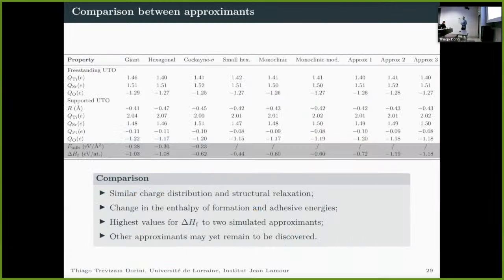And here are some general properties for all these phases. Well, it's interesting to notice that we did not find any particular difference in relation to the structural relaxation or the charge distribution of these phases. As you can see, for all these phases, their parameters do not vary very significantly. What actually changes is first the adhesive energy, as we see that it depends on the amount of titanium per area on these oxide approximates.